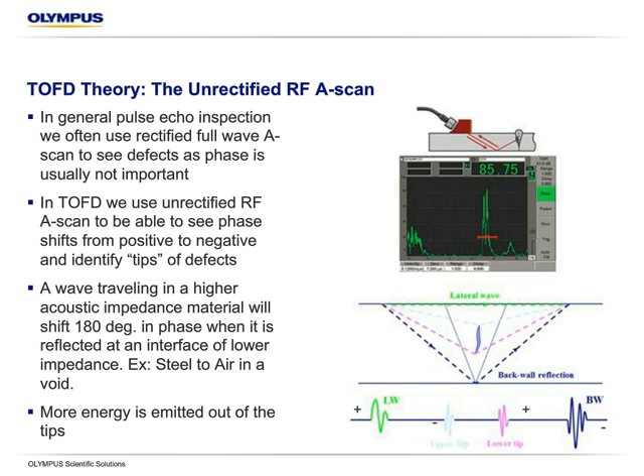The reason for this is we just want to make sure that we can detect small flaws. We're worried about amplitude. It's usually the way to display it. And in a lot of thickness and delamination, composite type applications, we might actually look at the actual positive and negative separately. And that's in fact what we do with time of flight diffraction typically. We actually look at the RF or unrectified RF signal because we want to be able to look at the peaks of both the positive and the negative energy. The reason for this is it allows us to use TOFD as a very accurate measurement tool.